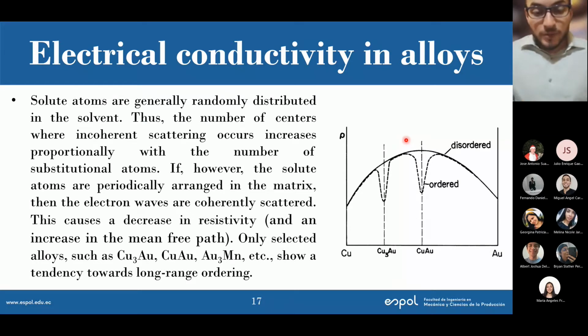So if I have pure copper, no resistivity, not a lot of incoherent scattering, pure gold, the same. If I have 50-50 copper gold, 1-to-1 atomic ratio, look at that, highest resistivity, because of this concept here, and it makes sense. The number of centers where incoherent scattering occurs increases proportional with the number of substitutional atoms. So if I have a 1-to-1 atomic ratio, I have a high number of substitutional atoms. Therefore, and even according to Matthiessen's rule, I have a lot of incoherent scattering processes, and that gives me a high resistivity. Again, I'm talking about the disordered state, right? Just random distribution.